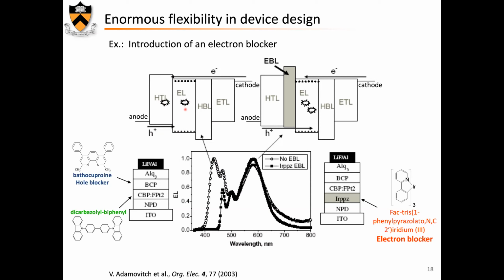So what do you do? Because you can insert, without creating defects, another material. You insert this IRPPZ material, which has a very high LUMO, which creates a block for electrons. Electrons cannot go over this barrier, and therefore all the recombination happens in this EL. And that cleans up considerably the spectrum of emission.